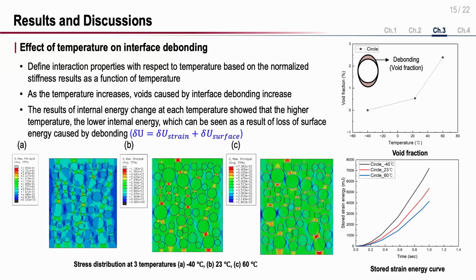And these are the results of our simulation. As you can see in these figures and graphs, as the temperature increases, voids caused by interface debonding increase. And the results of internal energy change at each temperature show that the higher the temperature, the lower the internal energy, which can be seen as a result of loss of surface energy caused by debonding.